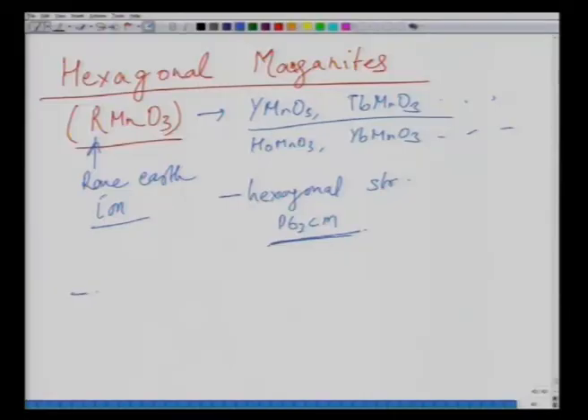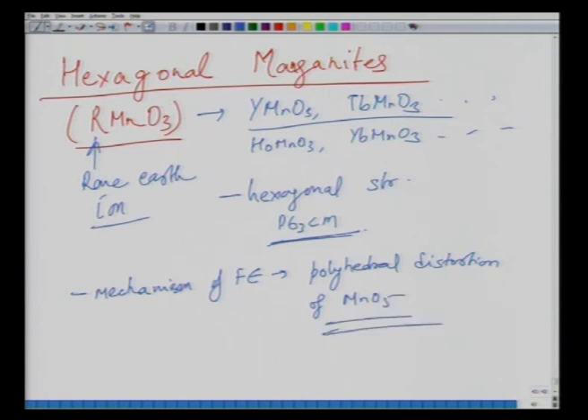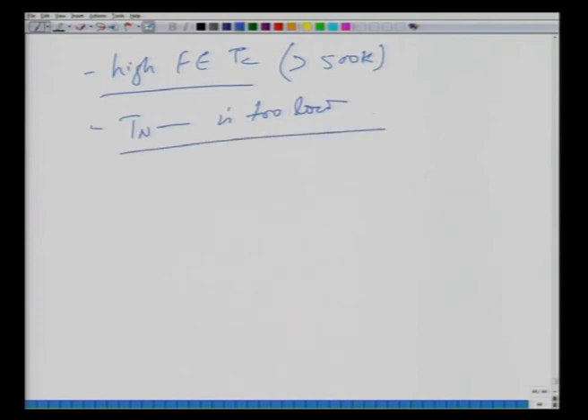So again, the mechanism of ferroelectricity is because of polyhedral distortion of MnO5. So this is the difference you have with respect to other cubic or pseudo cubic structures. Now the advantage with these materials is that they have high ferroelectric transition temperatures, typically higher than 500 K. However, the Néel temperature is too low, and this is what results in these materials not being very useful for practical applications. Now I'll show you some material examples.